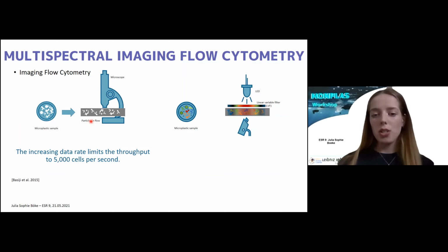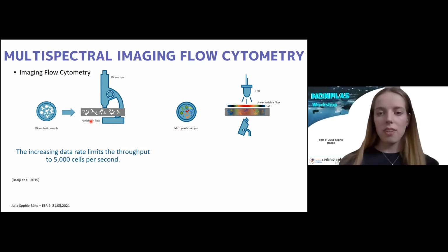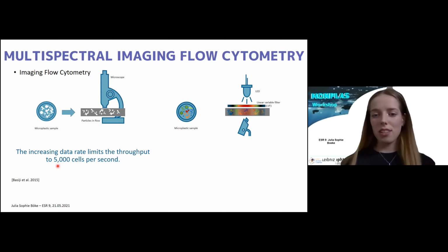So basically similar to what we've seen from Atif earlier. And now if we would get rid of this imaginary laser that we unfortunately can't see right now, and replace it with this microscope setup here, we unfortunately lose a bit of the throughput, because here you see that we now limit ourselves to about 5,000 cells for this method.